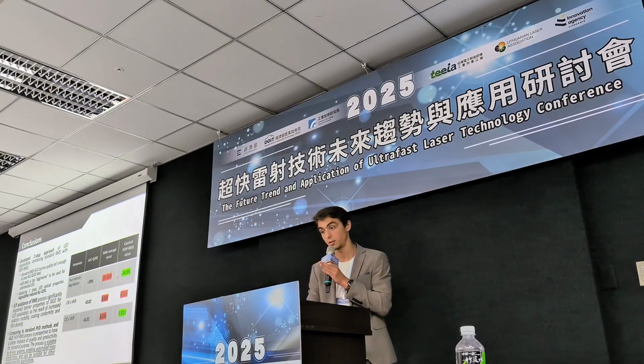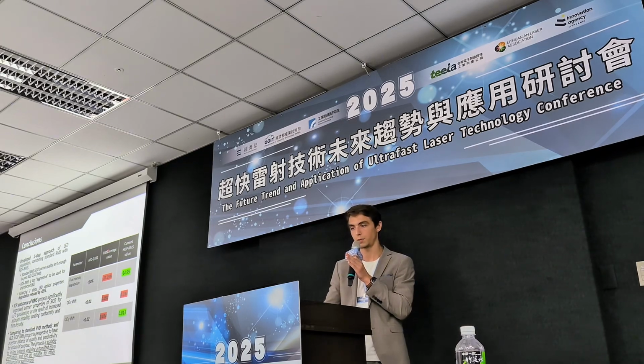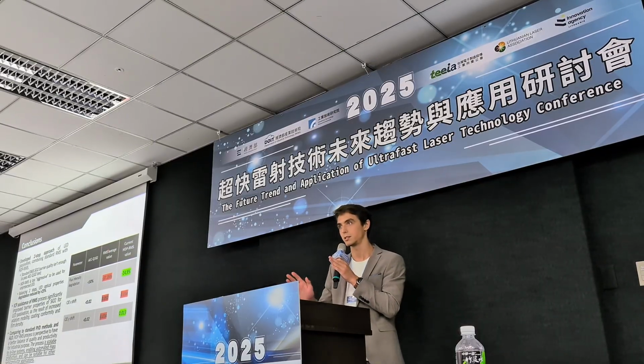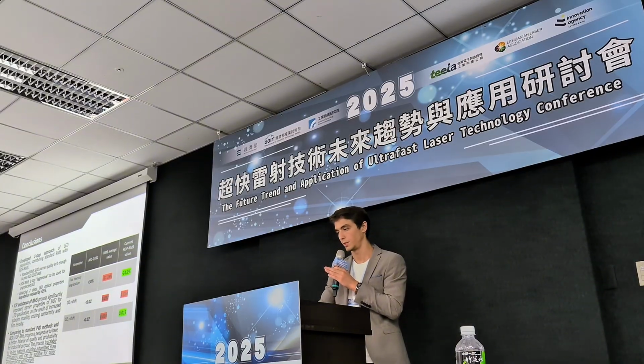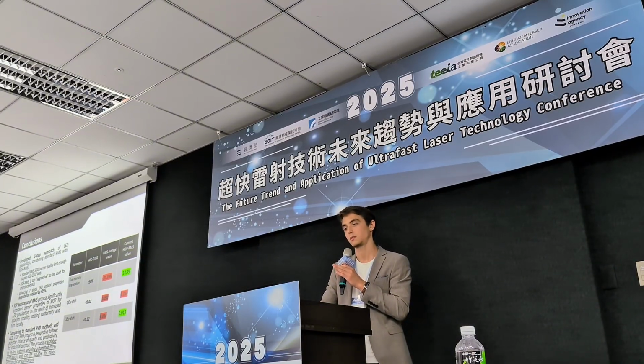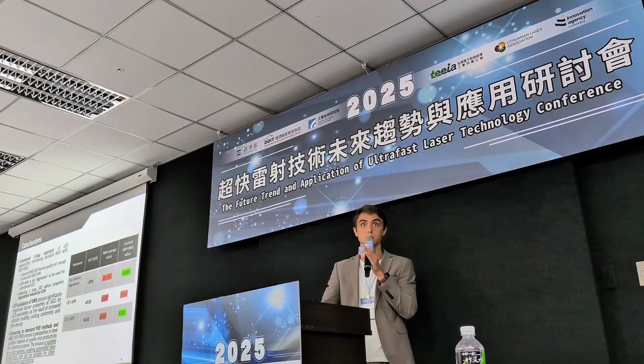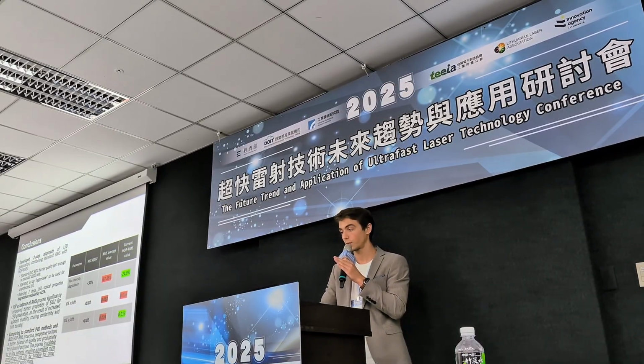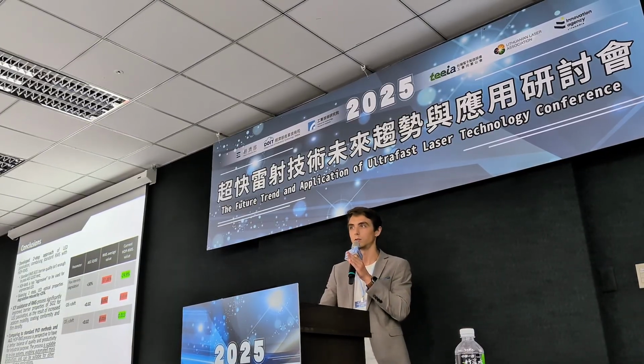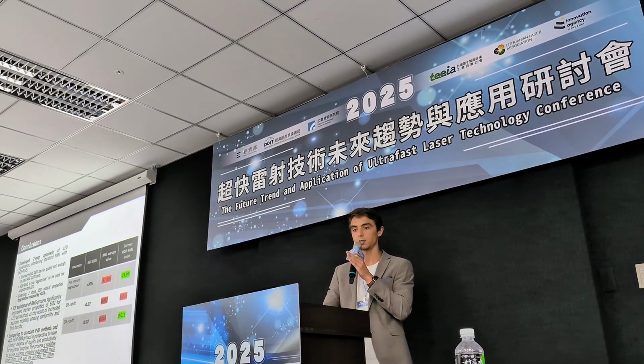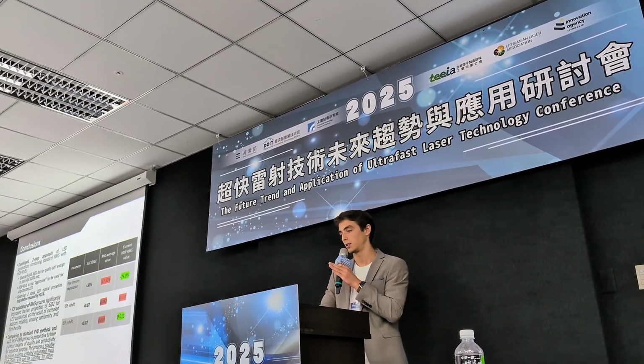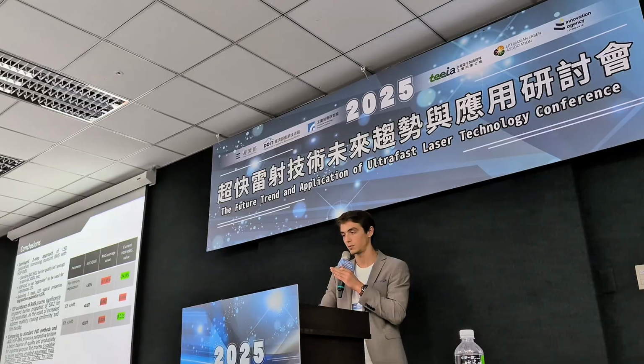For example, for such a coating, high-density plasma reactive magnetron sputtering is around a 3-minute process, but for ALD it's around 2 hours, plus or minus. So it's very beneficial. This method, reactive magnetron sputtering, is also very scalable, and now we are moving forward to integrate this process into mass production. First of all, to improve the initial quality of the LED substrates, because when the customer sends LEDs to us, they are already partially oxidized. We are going to integrate our system into a mass production system and move forward to meet all the requirements.